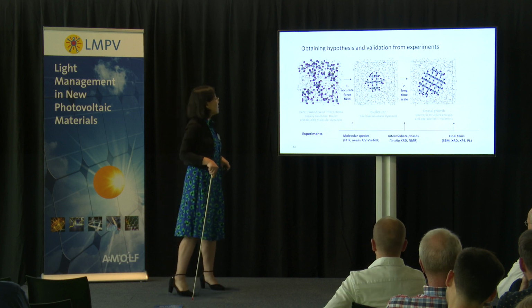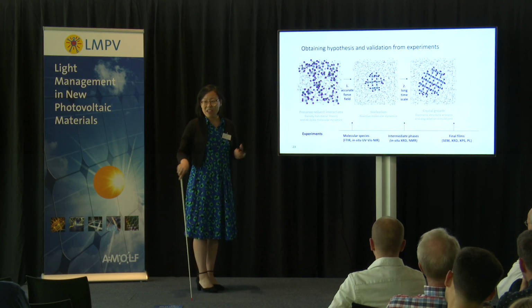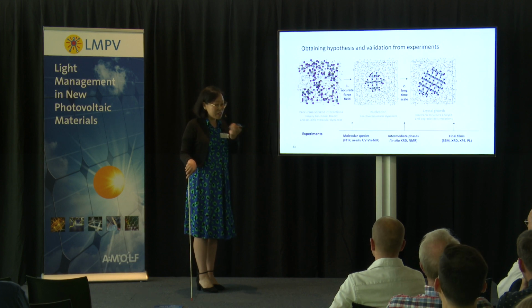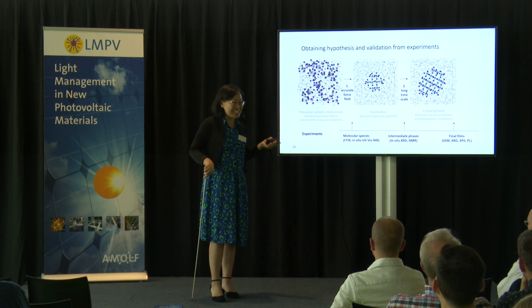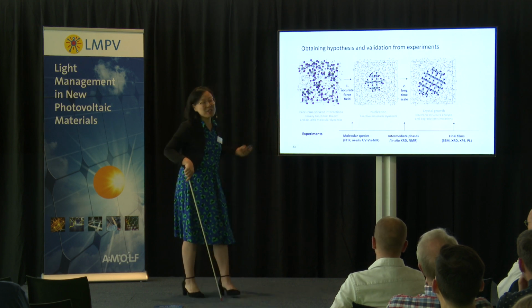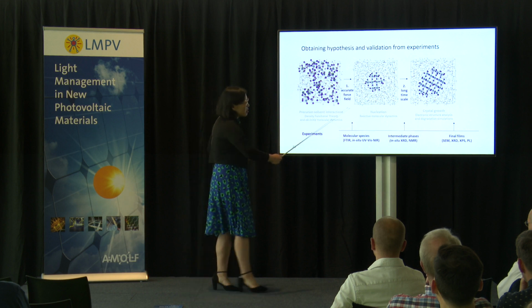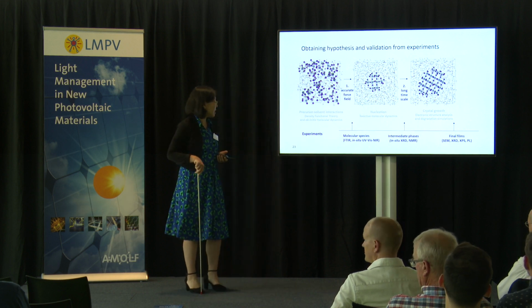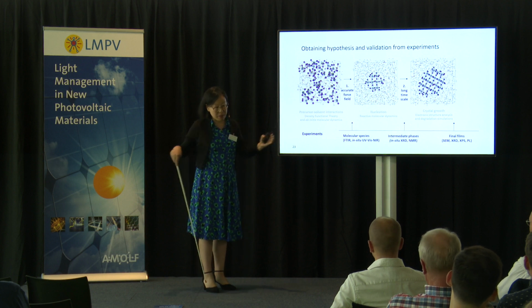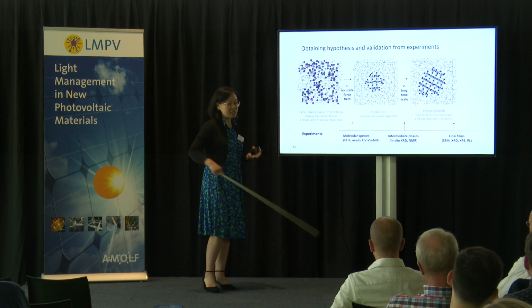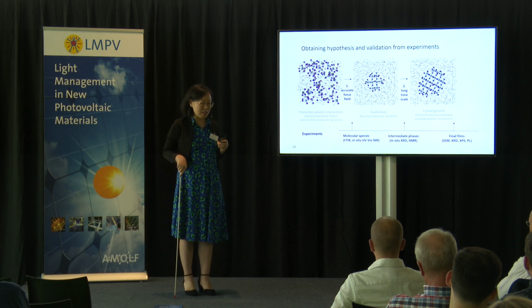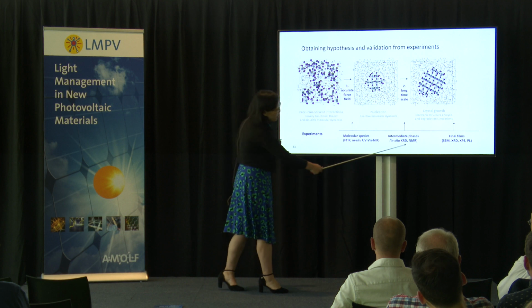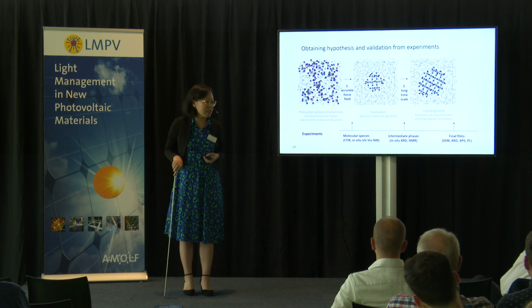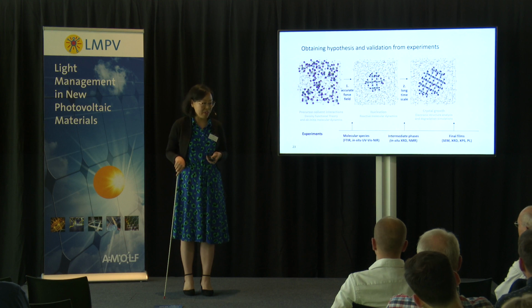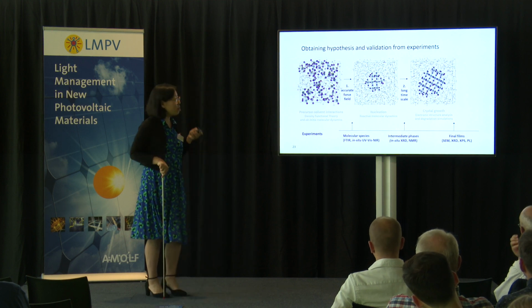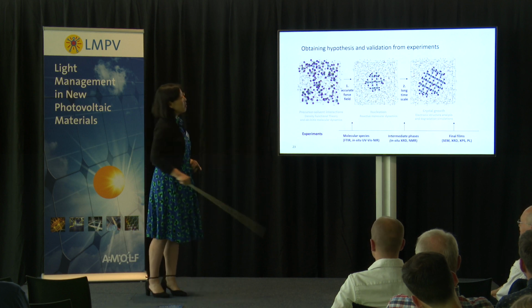To do this is actually more challenging than you would imagine, because in the lab, when you make the film, in a few seconds you get a nice film, but in the simulation, it takes minutes, days, months. This is a very slow process. So we actually need a lot of methodology advancement here to be able to simulate that. The most important is to get accurate potentials, and also to push the slow reaction to actually stage it in the simulation. To do this, we need a lot of collaboration with our experimental colleagues to help us develop models, but also validate them. This is very challenging, so I hope 5 years later I can show you exactly a beautiful crystal I can simulate.